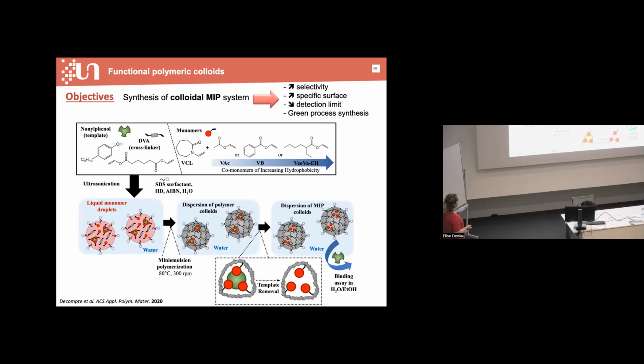And our idea was to use our microgel of vinyl caprolactam units, which can be in specific interaction via H-bonding with the nonyl phenol, and using a hydrophobic comonomer, and we studied the influence of the hydrophobicity of the comonomer on the network. The synthesis of this colloid MIP is very interesting because it could increase the selectivity, increase the specific surface, and decrease the detection limit of the micropollutant while using a green process, because we use a mini emulsion polymerization.